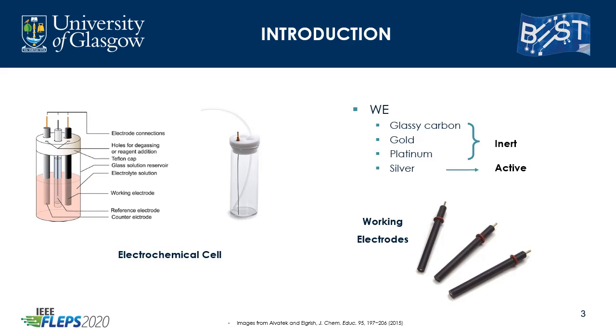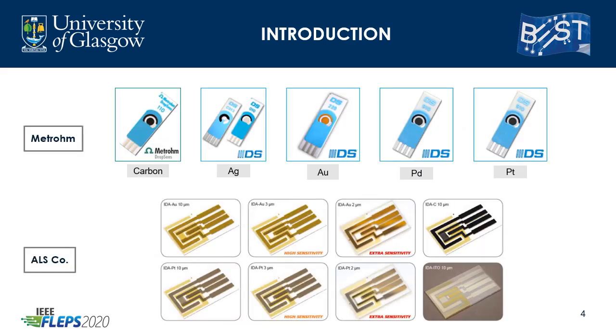Common materials are carbon, gold, and platinum electrodes, with the most important aspect being their inertness at a potential window of interest. However, silver can also be used as an active working electrode, for example, in electroplating, because silver is quite reactive. One thing that is interesting to notice is the electrodes are quite well protected with inert materials as to make sure there is little to no interference in the experiments. However, this can be a bit different when it comes to printed electrodes.